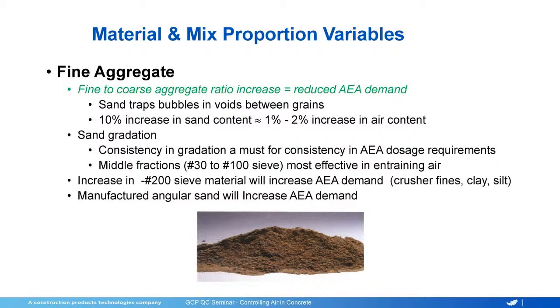A number of customers that I work with have worked with their aggregate supplier to say, I know what ASTM says, I know what the DOT says, but I need this range. In one case, we've got one customer that, because of the type of concrete he places in his precast plant, it's not just about air, it's about stability, and he has a minimum of 15% passing that 50 sieve because what he's doing is just not going to work if he gets less sand than that.